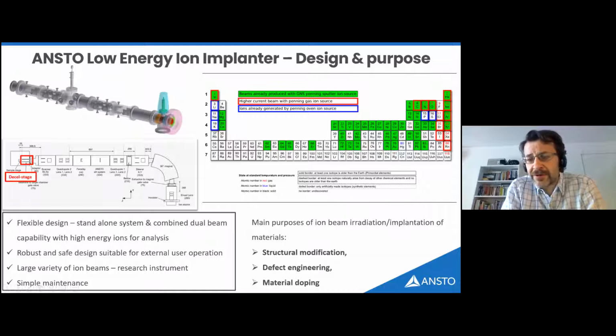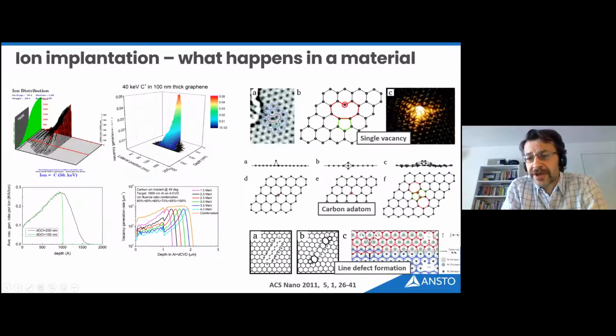So the main purpose of our ion implanter is to produce changes or modification of structure of materials, to produce defects. We can produce isolated defects, which can be utilized for quantum sensing, or we can produce a large number of defects, which induces significant changes to the material, or even doping. So what happens when we irradiate the material with a low energy ion beam?